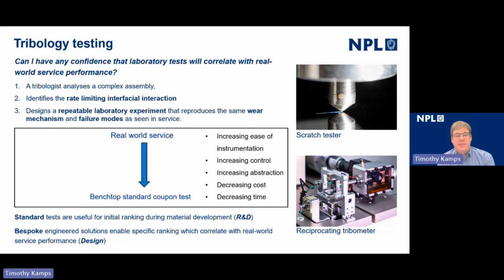So when we go from a large assembly down to a standard benchtop test, each step that we take away from the full assembly, maybe going to a sub-assembly, then using component parts, and then moving on to standard coupon tests, we increase the ease of instrumentation, and that allows us to increase the precision and accuracy of the measurements that we make. We increase the control that we have, so distribution of results that appears to be attributed to random error can be reduced because the input variables can be more tightly controlled.